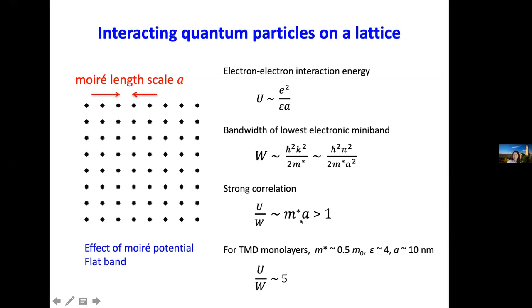For transition metal dichalcogenides, the particle mass is on the order of half electron mass, and the dielectric constant is on the order of 4. Then for a typical Moire lattice period of 10 nanometer, this ratio is around 5. But when you have a strong Moire potential, this will have flat band and significantly enhance this factor.